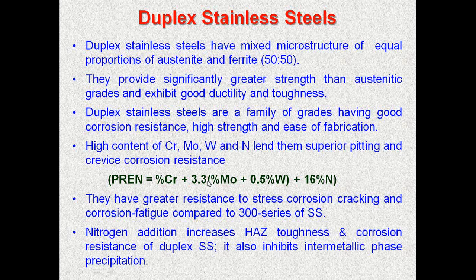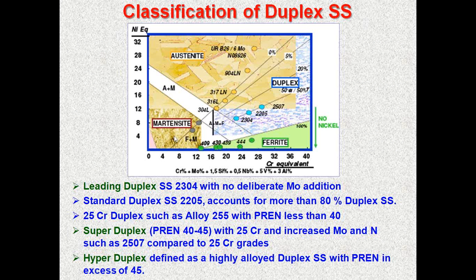In this case, a very high nitrogen is added in duplex, which increases heat affected zone toughness and corrosion resistance in these alloys. They also inhibit intermetallic phase precipitation. If you look at duplex, they are neither austenite nor ferrite, they are in between. You can see here the border of austenite and ferrite, the 50-50 duplex classes.